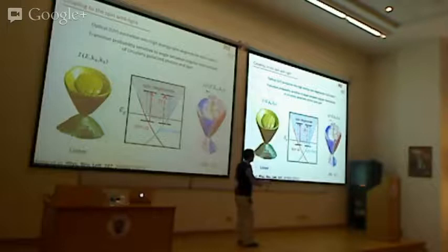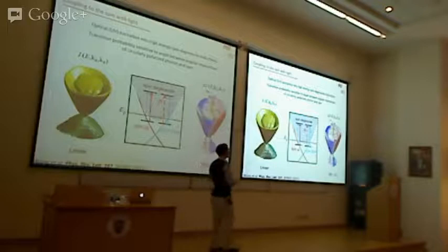The pattern obtained shows that for the bulk states, there is no difference between right and left, which makes sense because bulk states are degenerate. But for the surface states, you can qualitatively see the spin texture — red is one spin sign, blue is the opposite. To turn this into quantitative spin information, we performed theory calculations on the Hamiltonian with spin-orbit coupling, adding light as a perturbation as the vector potential. We showed that the matrix elements are linked to the expectation values of Sx and Sz — the x and z components of spin.